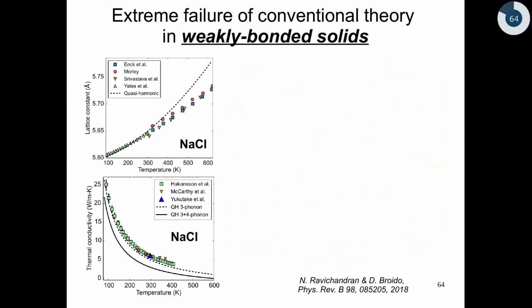So I'll just take a couple of minutes to show how we are able to even capture the failures of the conventional theory for thermodynamics as well. So in weakly bonded materials like sodium chloride, which is an ionic crystal, when you do the conventional quasi-harmonic approximation for the free energy, you see that the lattice constants are significantly over-predicted compared to the experiment. In the thermal conductivity also, if you do the full calculation, including 3 and 4 phonon scattering, the conductivities are much lower than the experimental measurements.